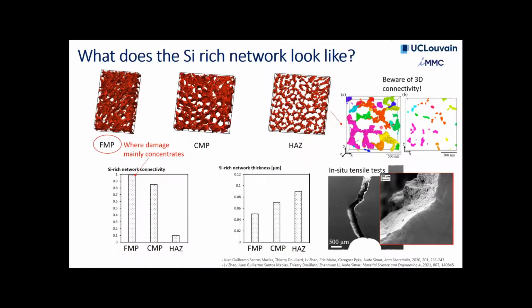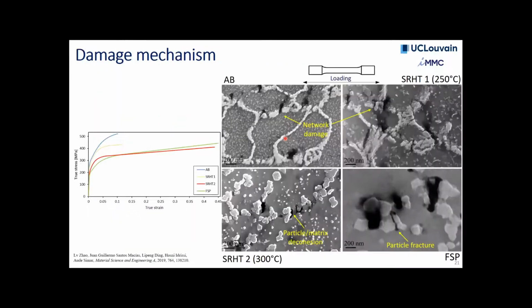But if you look at the larger scale, you actually have some connectivity in the heat affected zone. So we're really seeing in the heat affected zone that we have a bit of connectivity still. So I was still looking at the as-built material. Now let's look at all our heat treatment conditions.